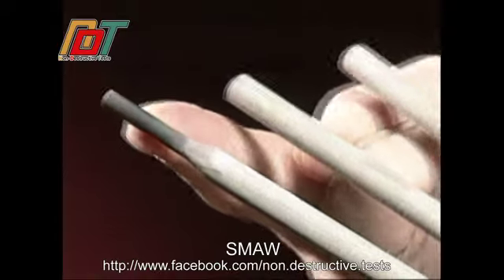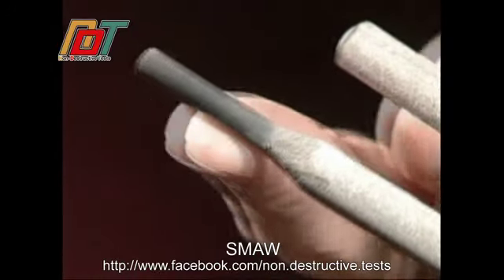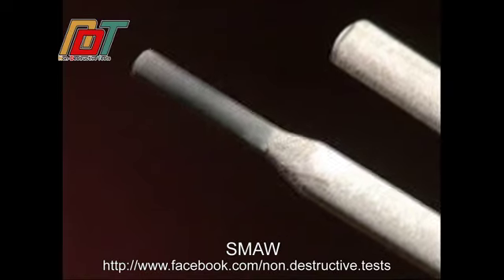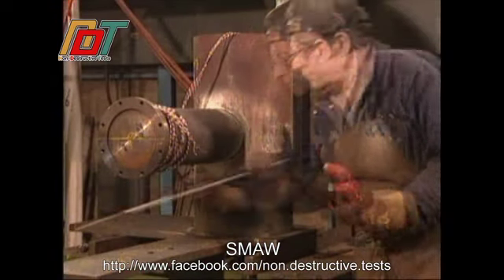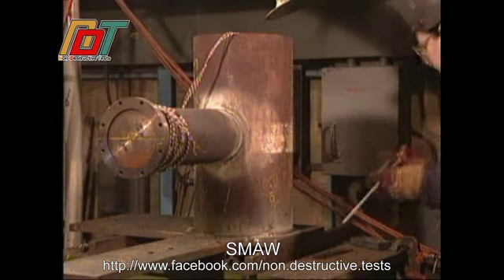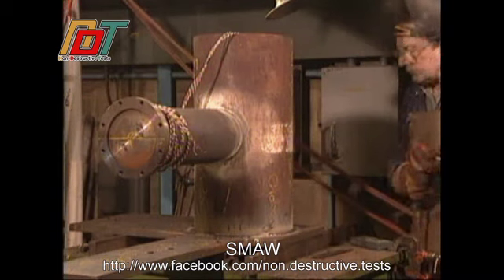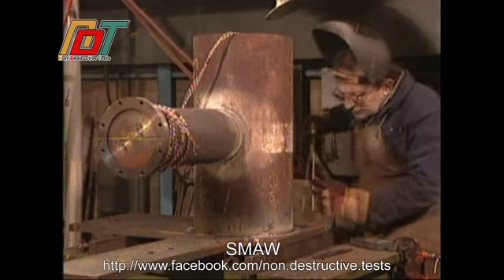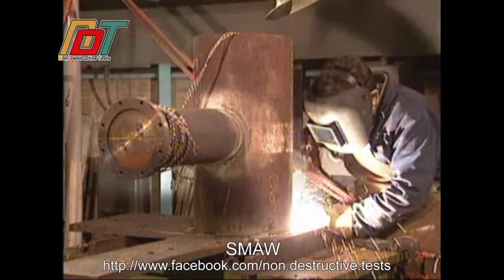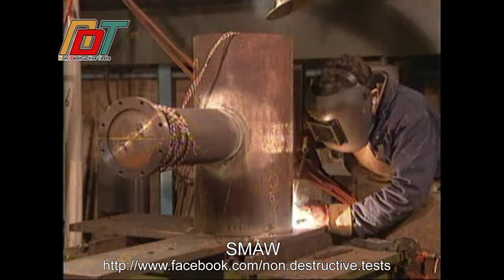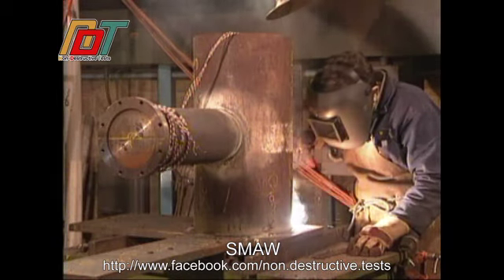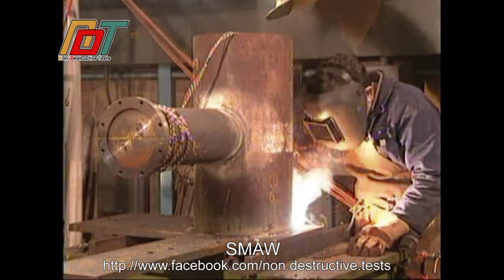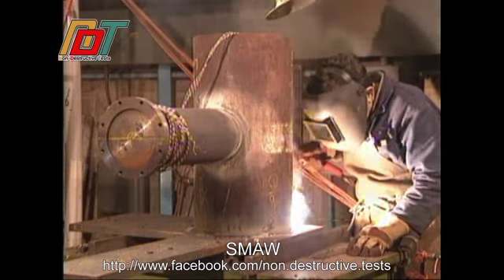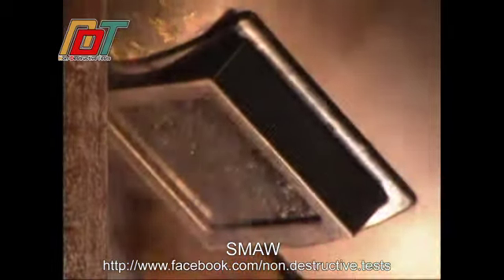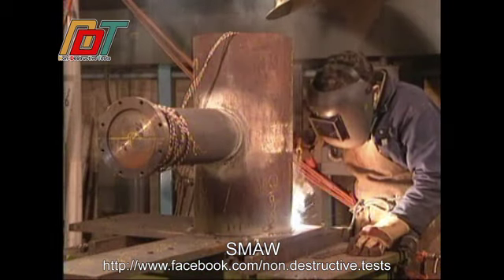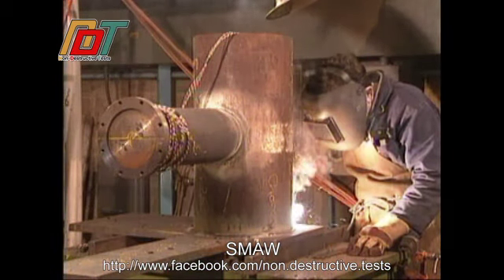Here the coating consists of calcium and other carbonates and fluorspar bonded with sodium or potassium silicate. In the heat of the arc, the carbonates dissociate, releasing carbon dioxide, which acts as the shielding gas. To further reduce moisture content, they're frequently baked immediately before use. Low hydrogen electrodes are normally tested to demonstrate a weld metal hydrogen content of less than 15 cubic centimetres per 100 grams of deposited metal.